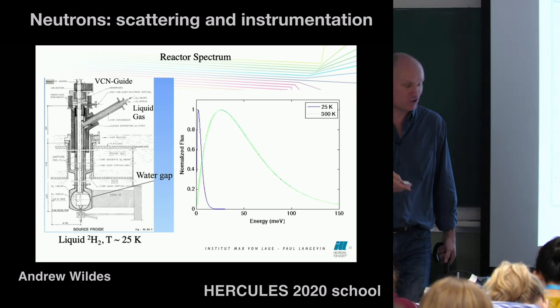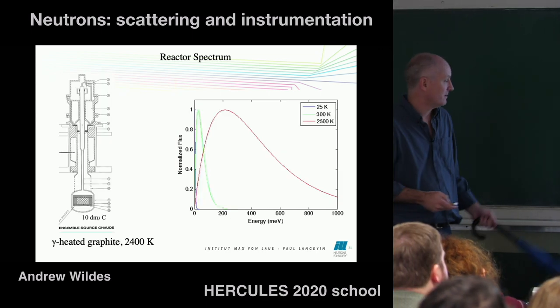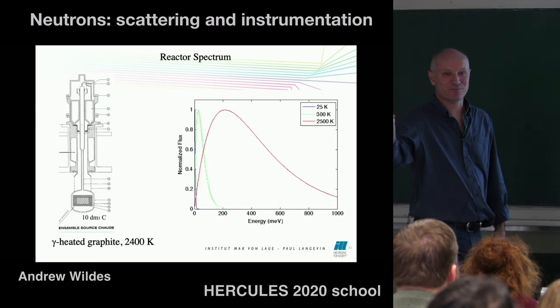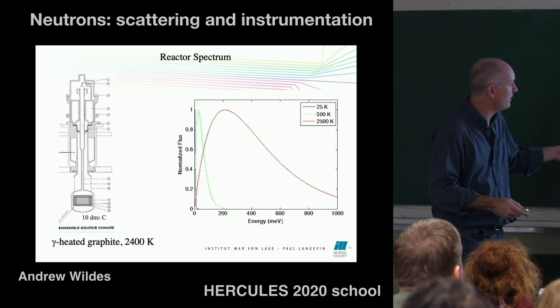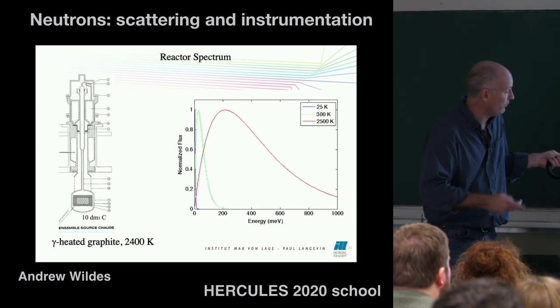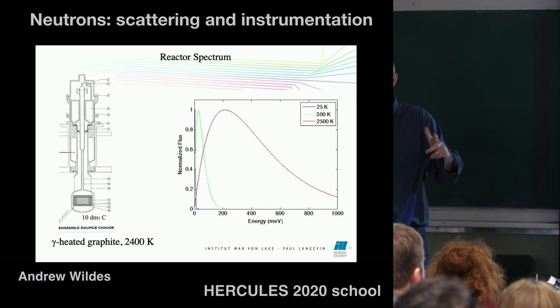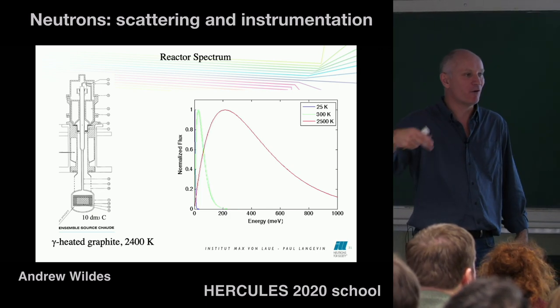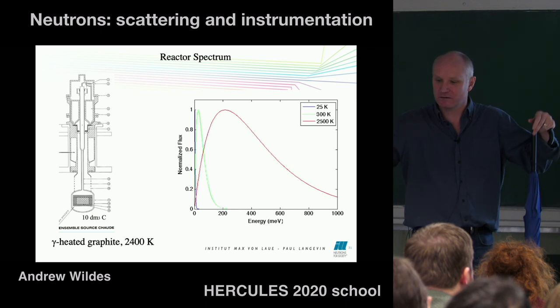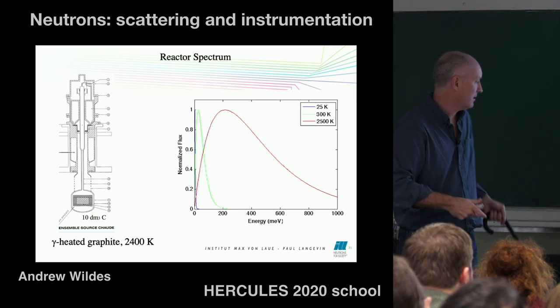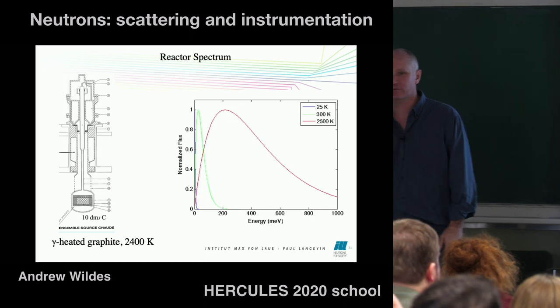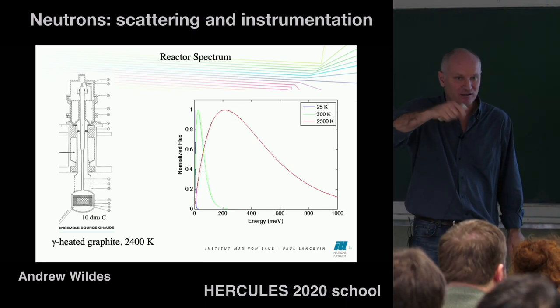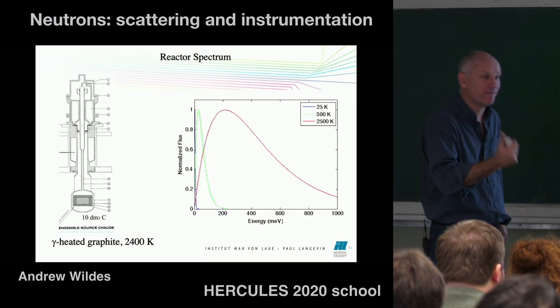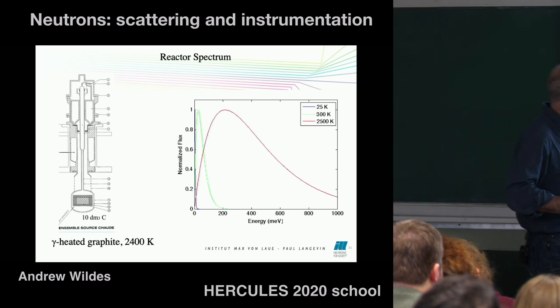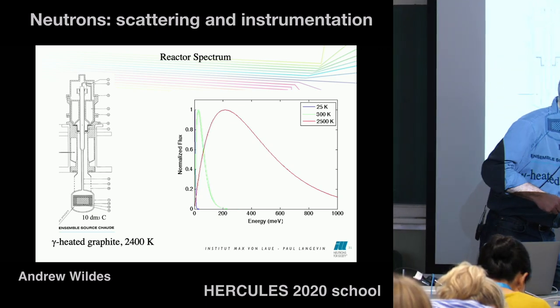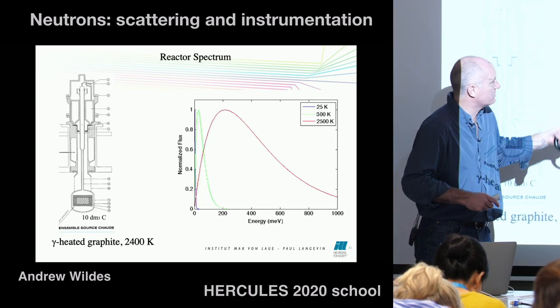There's another alternative, which is the hot source, all right? And I'm not talking about something with chili or anything like that. We've got one at the ILL. This is a ball of graphite, right? So you're producing a lot of gamma radiation inside the reactor as well. The gammas go into the graphite and they heat it up. And the temperature is of the order of 2000 Kelvin. The neutrons that go into that, they rattle around, they gain energy from the graphite, they get sped up, and they'll come out, and again, much higher energy, and then you're shifting your Maxwell distribution to the other side.